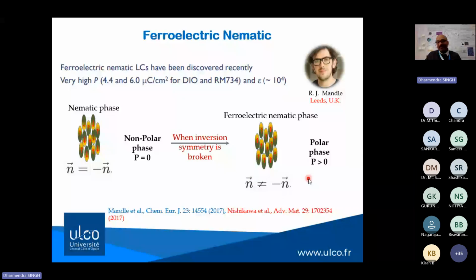These were the first reports by Mandle and one group from Nishikawa from Japan. But in 2017, they didn't coin this phase as a ferroelectric nematic. This was a polar phase, but in 2022, the name ferroelectric nematics was given for the first time. Their high polarization is around 4.4 for DIO and 6 microcoulomb per centimeter square for this material, and the dielectric constant is very high.